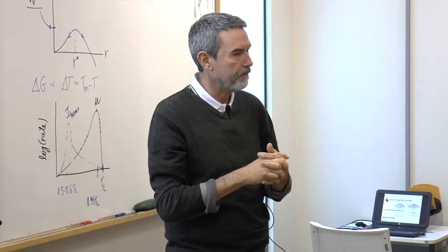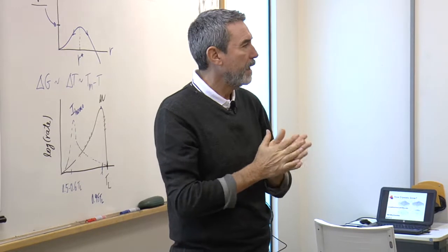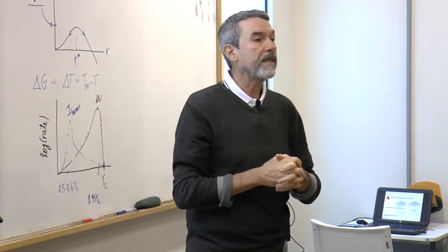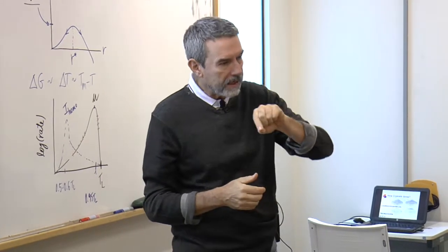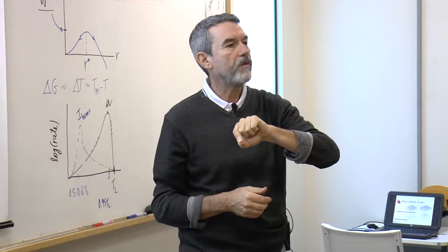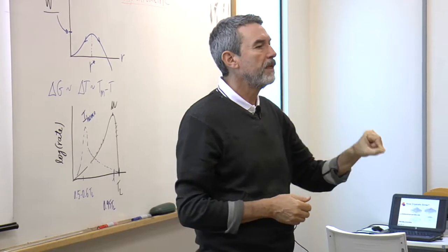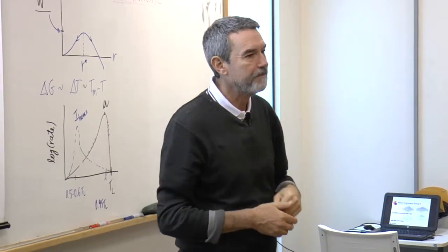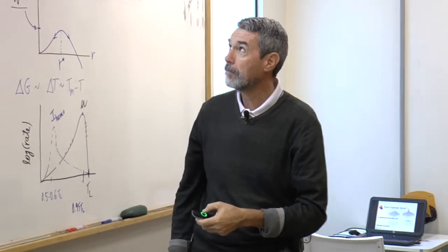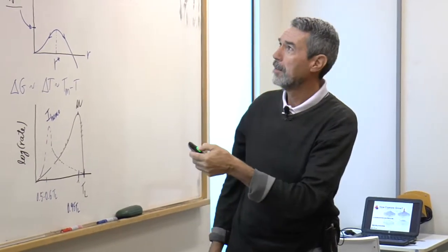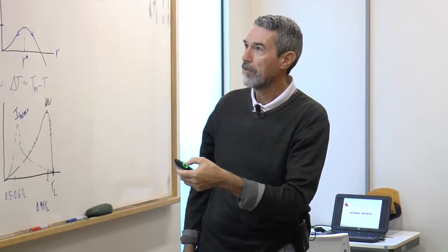Yes, it's possible. We have seen, at least in cordierite glass, I have worked with cordierite glass, and apparently it changes from a 2D mechanism to a screw dislocation mechanism. So that's the secondary nucleus I was talking about.